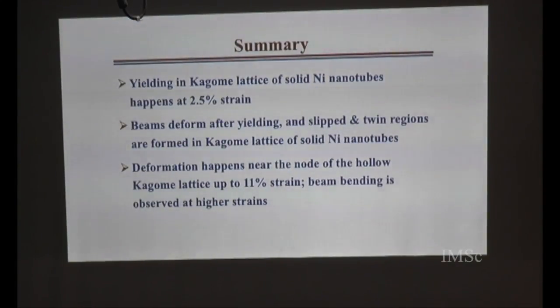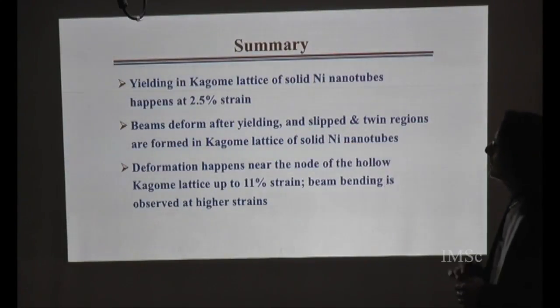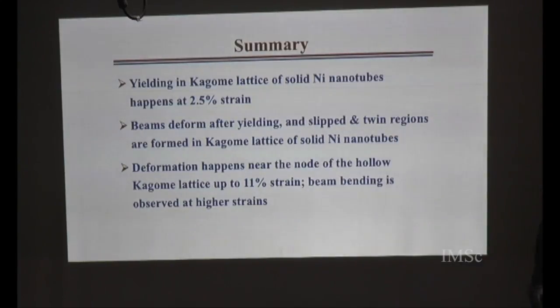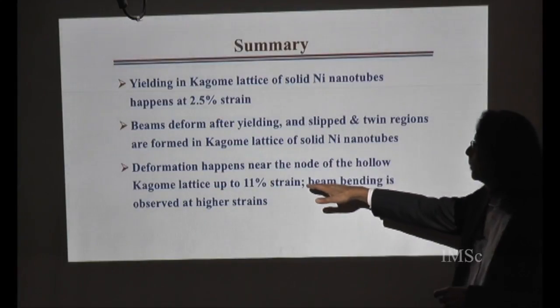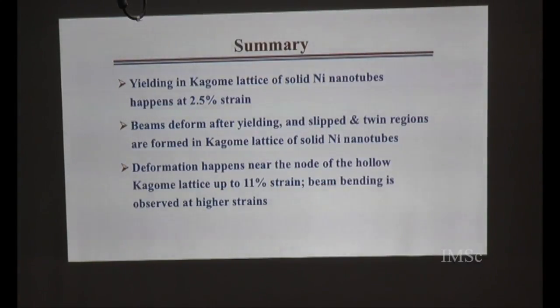So let me summarize this part. We looked at yielding in two kinds of system, one hollow nickel nanotube structure and the other one solid nanotubes. The difference between the two is that beams deform after yielding, and we see slipped and twin regions in the structure with solid nickel nanotubes. And in the case of hollow nickel tubes, up to a strain of 11%, we don't see any really deformation, and then beam bending is observed after that.